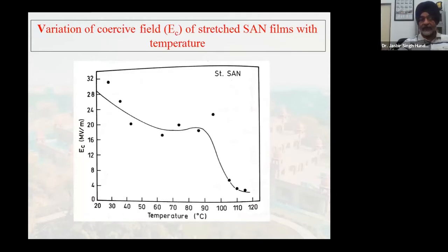And another thing, this hysteresis loop was studied at different temperatures. And we find that this loop starts vanishing when the temperature is increased. So when this coercive field was measured at different temperatures, with slightly heating it, we find this kind of variation, and there's a fall in Ec. There's a sudden collapse of the PE loop at higher temperatures, near the glass transition temperature of the film. There's a sharp fall at around 100, 105. The fall starts at around 90 and it's all over by 110. So that means randomization of dipoles is taking place, and the polarization is all lost.